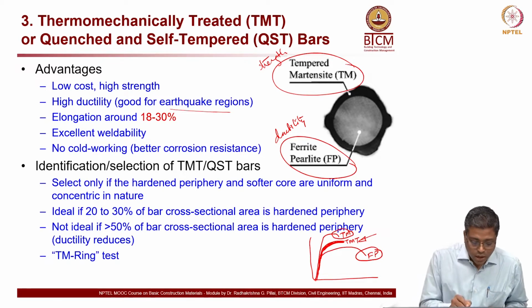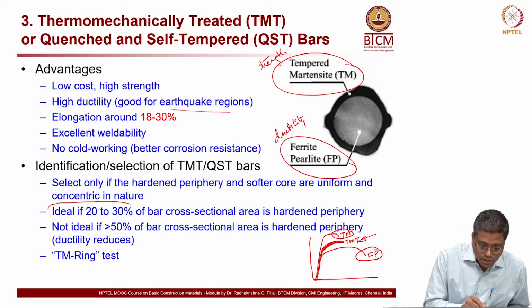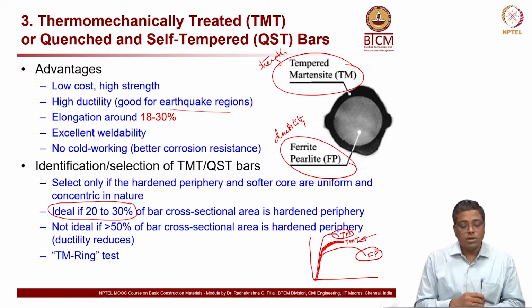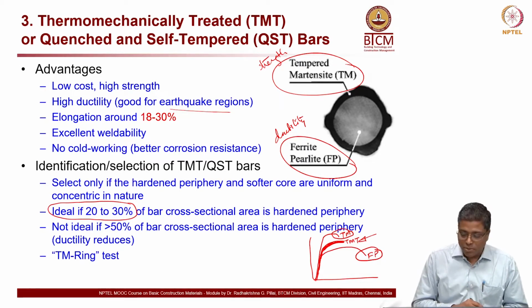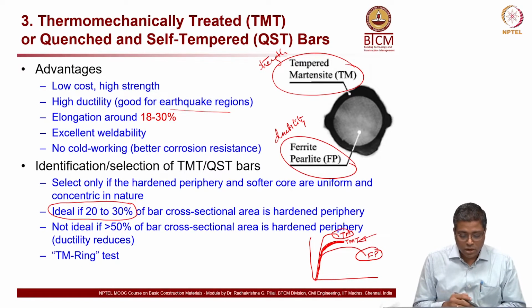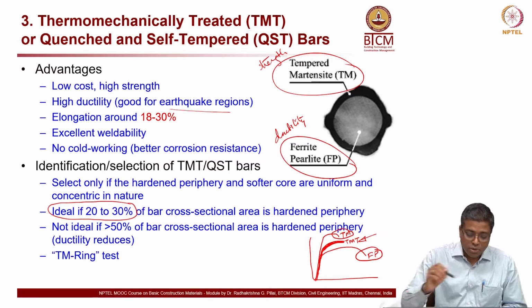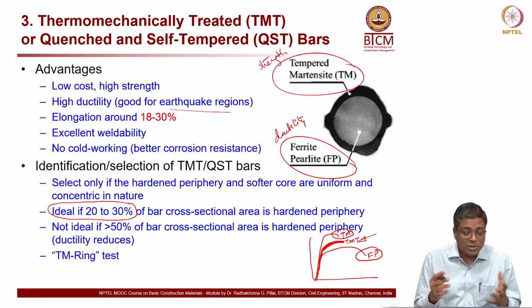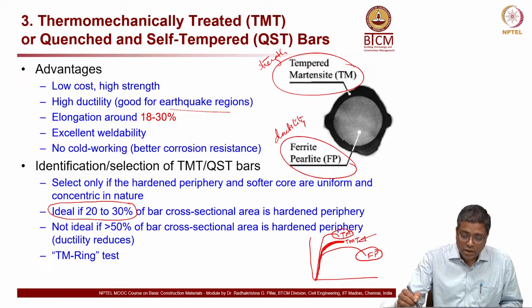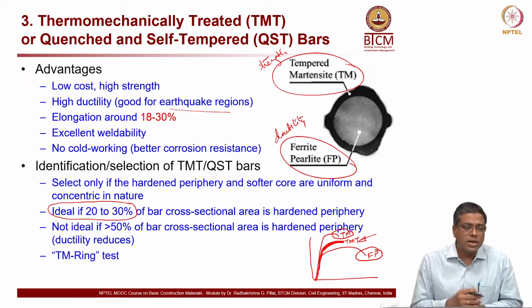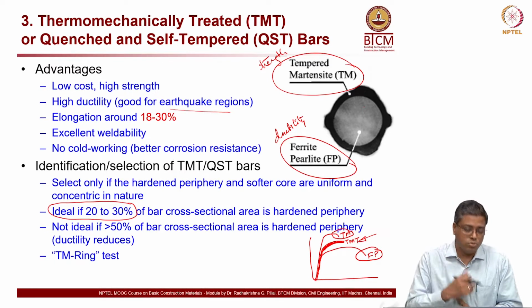Okay, now there are some specifications here. The bars are ideal if 20 to 30% of the rebar cross section area is hardened periphery, that is, the tempered martensite, and not ideal otherwise. See, if the dark color region and the gray region are not really uniform, these bars will not behave the way you want them to behave.